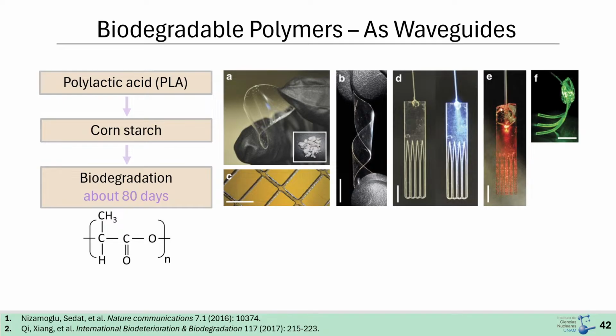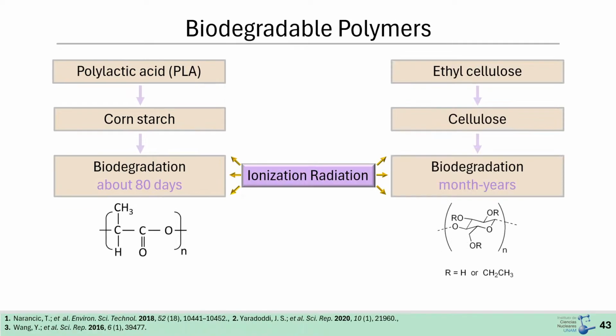So for the polymeric part, I'm interested in working with biodegradable polymers such as PLA. PLA already showed some waveguiding behavior. Taking advantage of the gamma irradiators that we have here, I also want to study how those materials basically degrade after exposing them to the gamma radiation. So polylactic acid is one of the most promising polymers. It's already 30% of the polymer that is used daily is PLA.